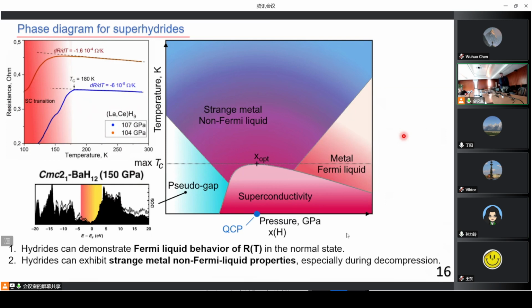But the phase diagram is somehow similar, because a distinguishing feature of the strange metal behavior of cuprates in the normal state is linearity of resistance in a wide temperature range. And in many cases for hydrides, we also see unusually linear dependence of resistance on temperature in a wide temperature range. That's why I placed such a big region for strange metal behavior and non-Fermi-liquid behavior of polyhydrides here as well.